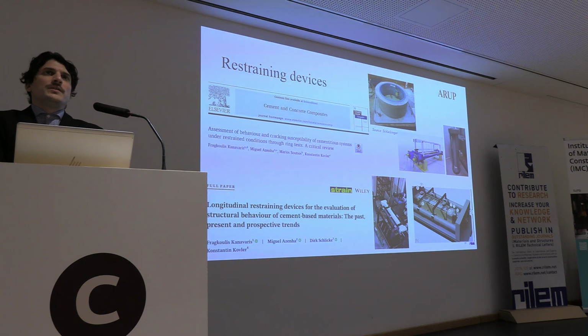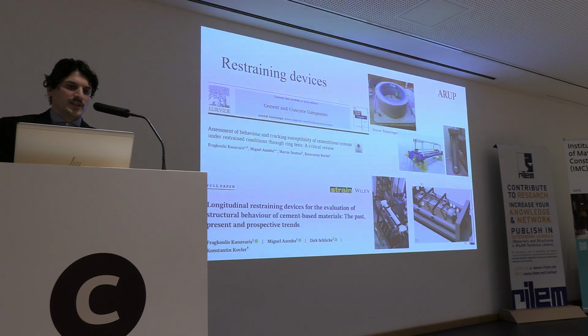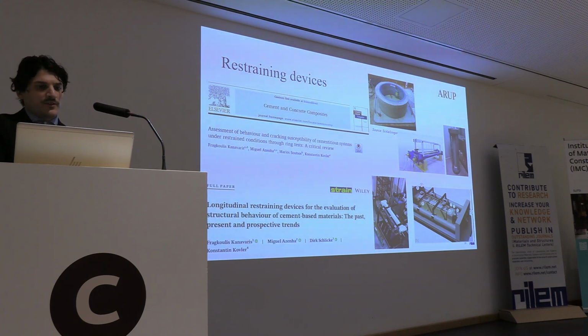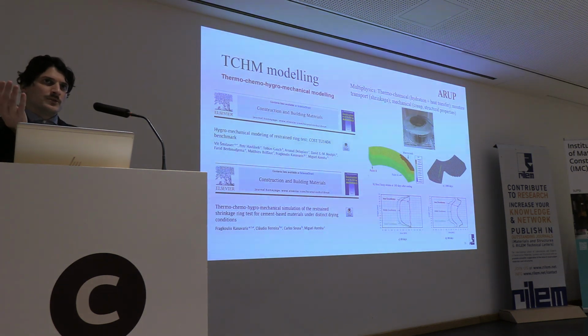And we led into the analysis of what restraining devices can tell us about the early age and long-term behavior of concretes with and without supplementary cementitious materials. And there I had the pleasure of working with one of the pioneers of this landscape, Konstantin Kovler, another RILEM legend, and we developed these in-depth studies on restraining devices, but also on advanced numerical analysis for predicting the multiphasic phenomena associated with concrete hardening, and particularly employing multiphasic models to account for hydration, so thermochemical moisture transport and mechanical models to account for combinations of hydration, shrinkage, and creep and structural effects.